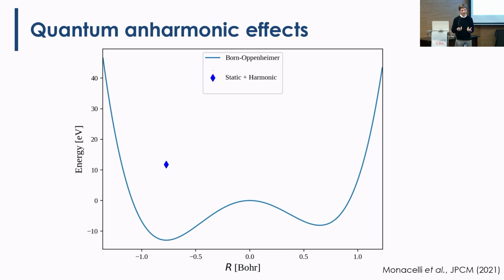That's this energy. Then we need to add the zero-point motion energy of the ions, right? Because at 0 Kelvin the ions also fluctuate with the zero-point energy, 1/2 ħω, right? So ω comes from the second derivative of the curvature here. Let's say we calculate that total energy, we add that to this energy, so this is the energy we get, right? Imagine we solve this, it's a 1D potential.